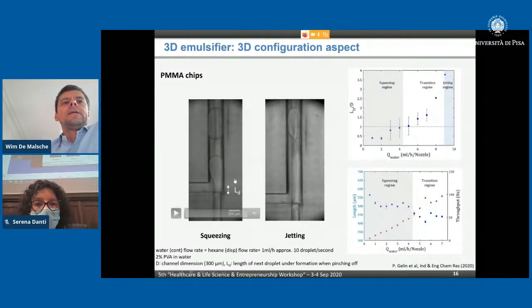And so this gives you an indication of instability. As this length scale increases, you get more and more into unstable regions, and you get into the jetting regime in the end. And as said before, when we are increasing the flow rate, we cannot just do this unlimitedly. There is one limitation, pressure, but the other one is that we're going into unstable regimes.